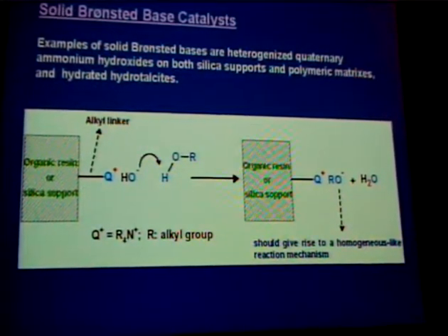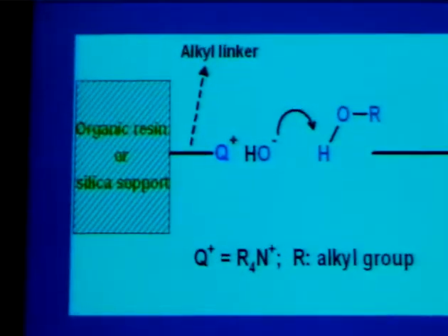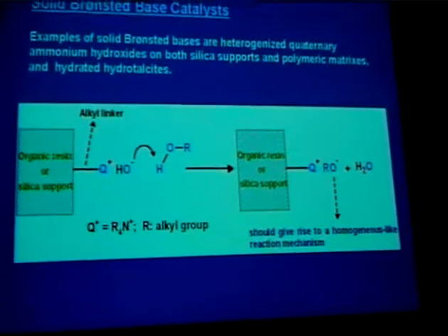And something that I had to say before I continue is that, in this case, look, you're forming water when you do this reaction. You don't want water present in this media, because any molecule of water can give you a molecule of carboxylic acid, and that carboxylic acid can neutralize your site. So you don't want water here. So the first step when using this catalyst is you have to wash this catalyst thoroughly with alcohol. So you convert everything to this and you wash out the water. That's the first step, and that's what we did.